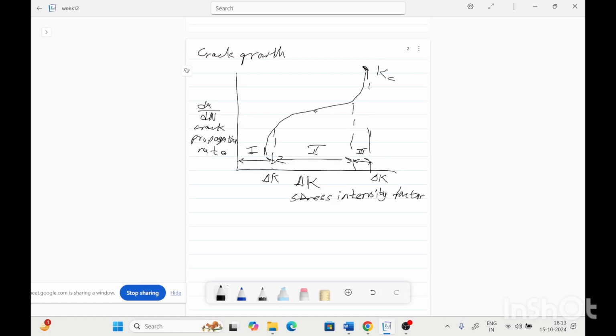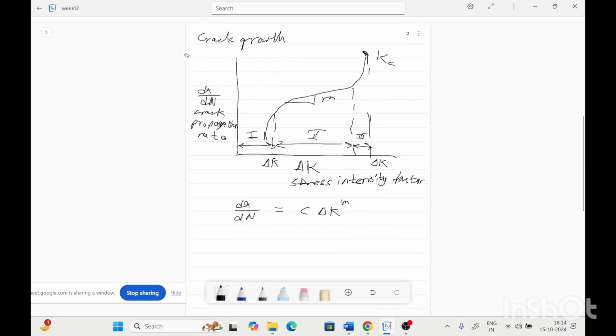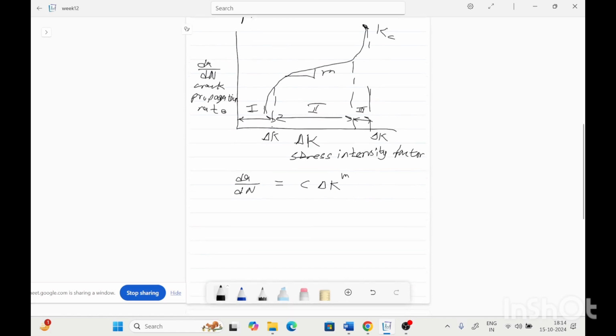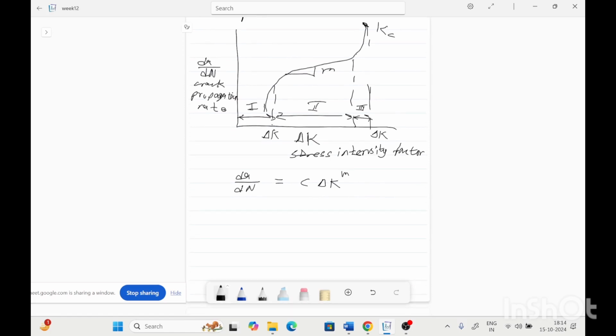And stage 1 and stage 2 follow a relationship of the crack growth rate with the stress intensity factor as C delta K raised to the power m. So the slope of this region will decide the crack propagation rate and the material behavior. So this is delta K threshold.